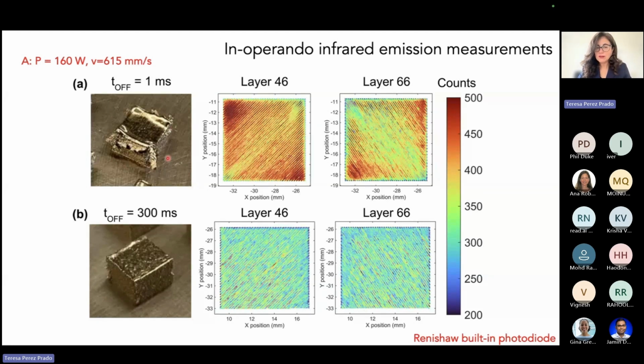So with no time delay, we knew it, we are in the orange domain. There is no dimensional stability. We cannot print. And here you have the emission maps for layers 46 and 66. We have, of course, this heat accumulation in the corners. Now, when we introduce this 300 milliseconds time delay, suddenly, yes, we can print a cube as we want, and you see that the emission decreases in the same layers. So this seemed that it could work, but what is important now is to check how we are doing in terms of density and amorphous fraction, of course.